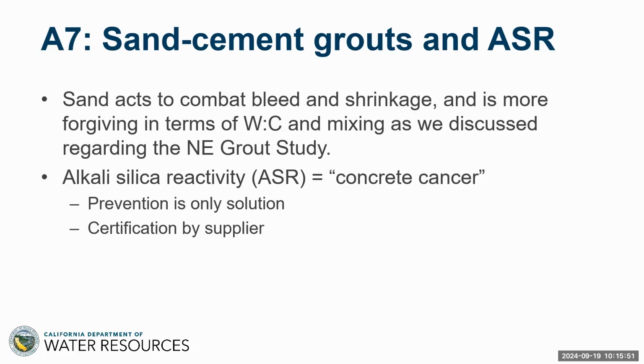One of our biggest dams in TVA, Fontana Dam, was completed in the early 1940s. And what AAR, or ASR, does, it causes swelling and therefore cracking. And that big concrete dam is still growing. You can accommodate it by cutting slots in the dam, to take the compression or the expansion, but you cannot stop it. It's an internally consistent, ongoing reaction. It doesn't need an external water supply to continue the reaction.